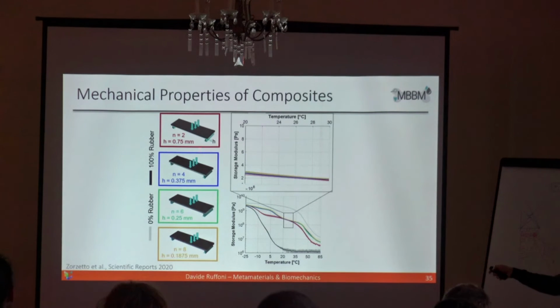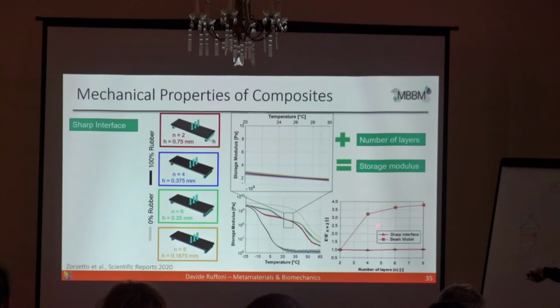Exactly the same system, if now the interface between the layers is sharp, actually you see that increasing the number of layers, the storage modulus stays the same. So we said, ooh, what is going on here? Why is it staying the same? Why don't we see the increase that is, you know, expected by beam theory?